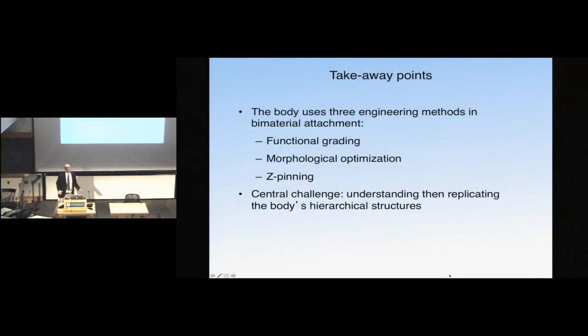So out of all of this, what do I want you to take away? The 3 points I'd like you to take away are that there are specific mechanisms that the body uses to attach tendon and bone. And you have intuition for all of them. They are the same mechanisms that you use to attach gum to a table. They are what we call functional grading, which is a distribution of material properties to make the mismatch in stiffness less severe. There's morphological optimization, which is smearing out the corners. And then there's what the composites community calls Z-pinning. I didn't use that term, but Z-pinning is the phrase that's used to interdigitate two materials and improve resilience.